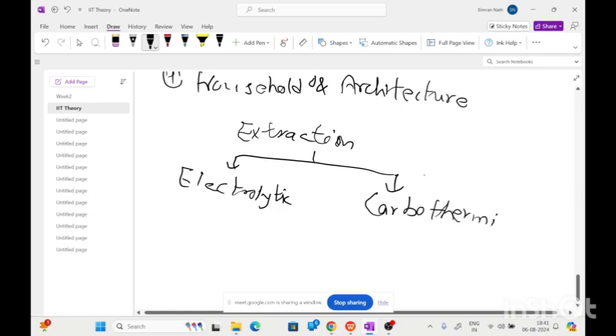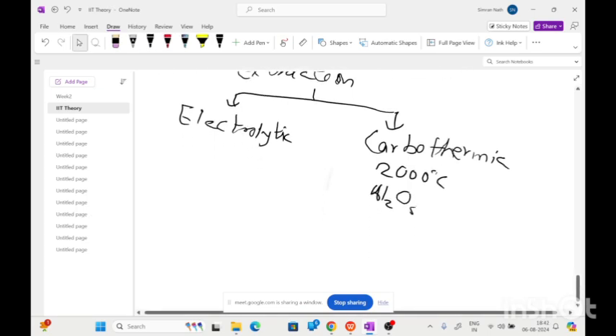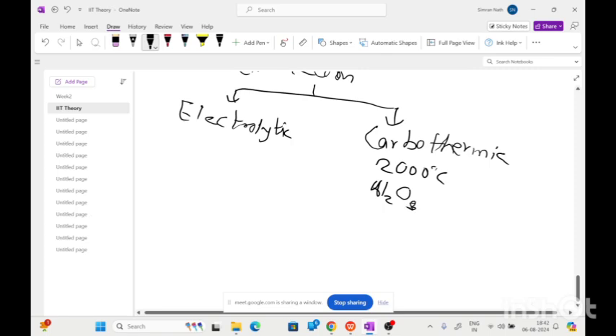the required temperature is around 2000 degrees Celsius to decompose the alumina, because aluminium oxide is a very stable oxide, and it requires a very high temperature for dissociation. So that's why carbothermic reduction is not used. In the electrolytic extraction method, there are two types of process: the Bayer process and the Hall-Héroult process.